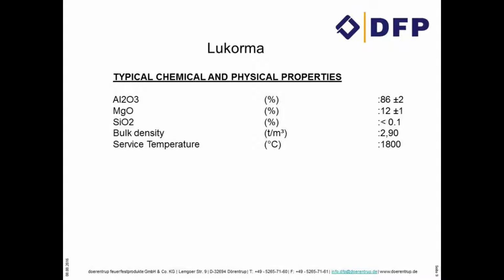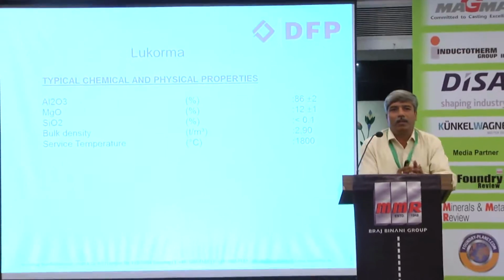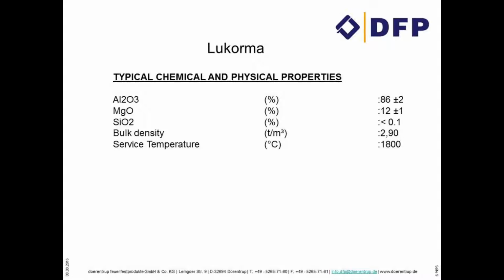The third refractory, which is neutral, was developed in Europe a long time back and has been used in Europe for about 15-20 years, but it was not adopted or popular in India. In the last 4-5 years, the neutral lining has become popular in India. The reason is that it can be used for acidic slag as well as basic slags, so it can be used for any kind of metal. But we normally recommend it only for steel melting. For cast iron melting, we still promote the silica lining with boron oxide. People normally use boric acid, which we now have to change to boron oxide.